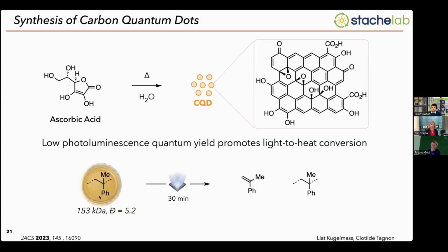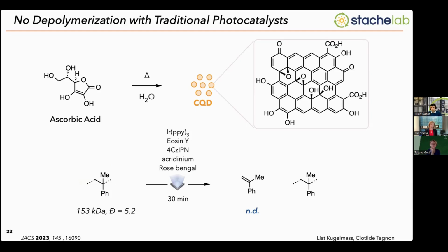And so we started with the model polymer. Liat mixed poly-alpha-methylstyrene with the carbon quantum dots. She made a film. She irradiated it for 30 minutes and then generated the alpha-methylstyrene monomer in 85% yield, with the mass balance just being leftover alpha-methylstyrene oligomers. Now, notably, this reaction does not work with your standard photocatalysts. So these are very common photocatalysts that we use for electron transfer, energy transfer, to promote all these different types of reactions.